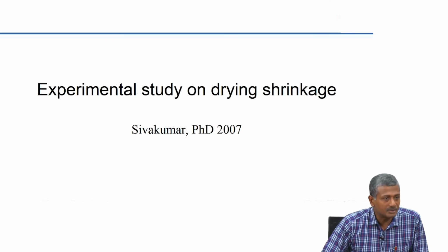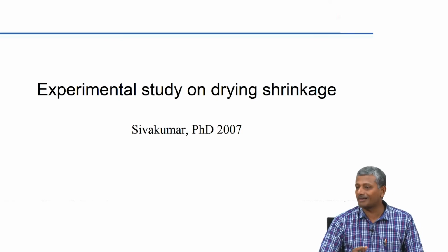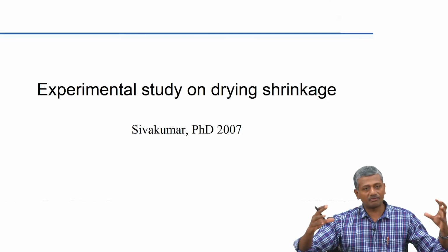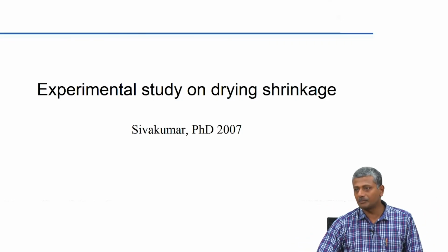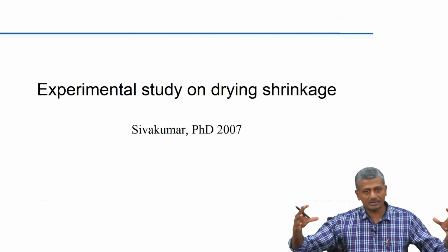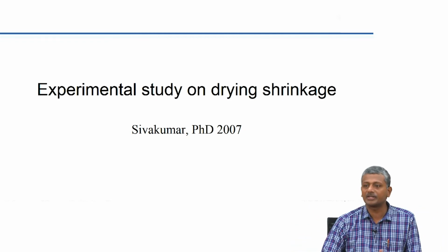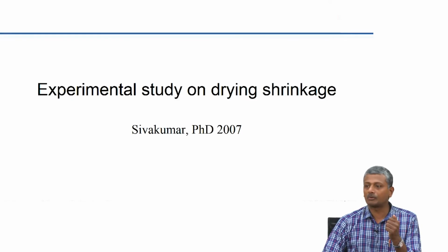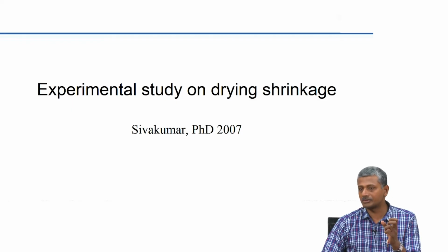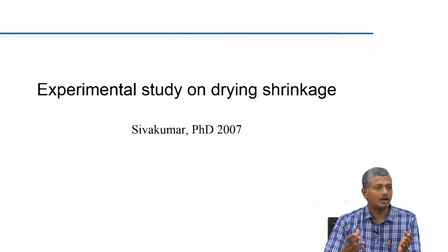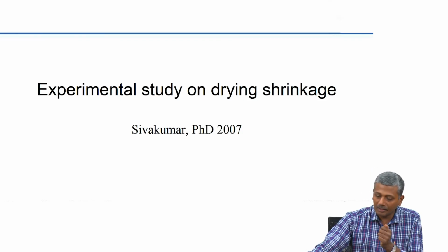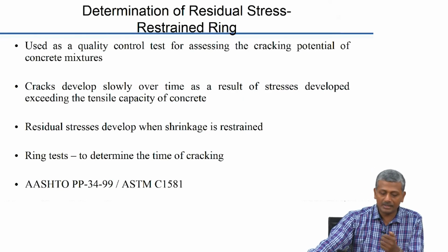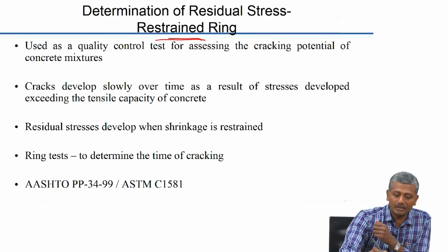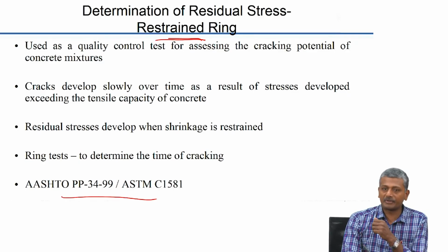As far as fibers are concerned, the ability of the fibers is to restrict cracking. If you allow the system to shrink freely, it will never crack, right, because there is no stress. Strain is continuously increasing as the length change happens, but there is no stress because there is no restraint. So, what you have to set up with respect to drying shrinkage is a measurement of the restrained shrinkage. That means, when shrinkage happens, if there is a restraint, how does it lead to the generation of cracking? And for that, there is a test called the restrained ring test, which is again an ASTM specified test.